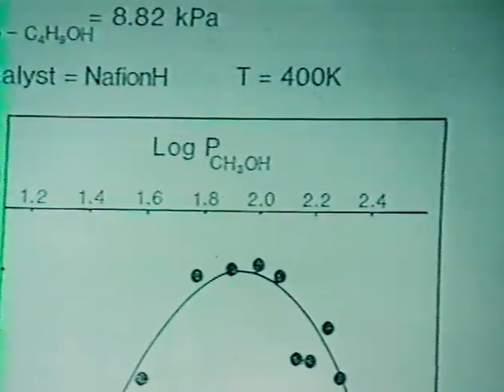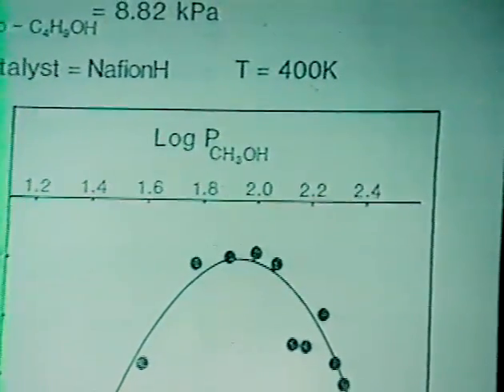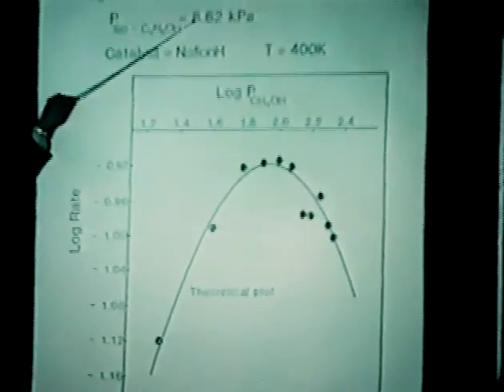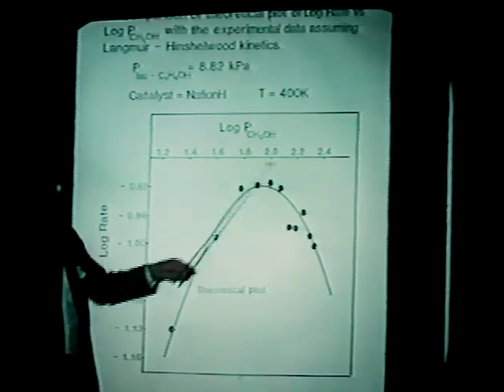Further, there's a competition for the acid site. The Nafion has SO3H groups on a fluorocarbon backbone. Now, these are the superacid sites. Now, if we keep the isobutanol constant and increase the partial pressure of methanol, we get kinetics. These are all steady states. We get kinetics such that the rate first increases, and then with further methanol addition decreases. It's a typical kinetics that tells you that there is a competition for the same sites between the two alcohols that are to be coupled.